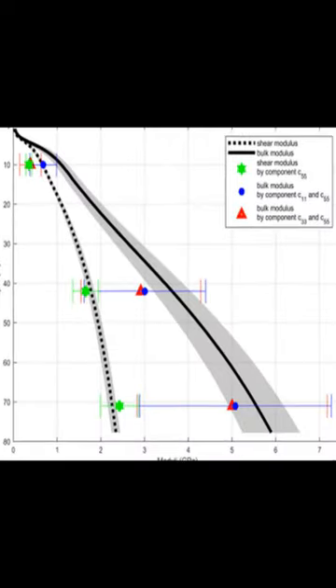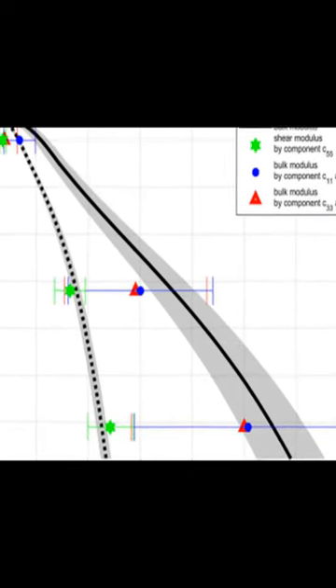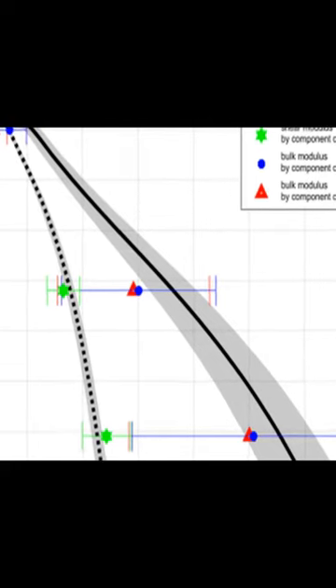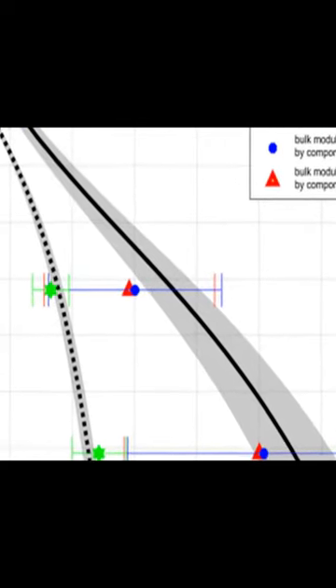The results showed that the elastic moduli from seismic observations and the structural FEM agreed within 8.5%, demonstrating that both methods provide reliable estimates of the elastic moduli of the firn.